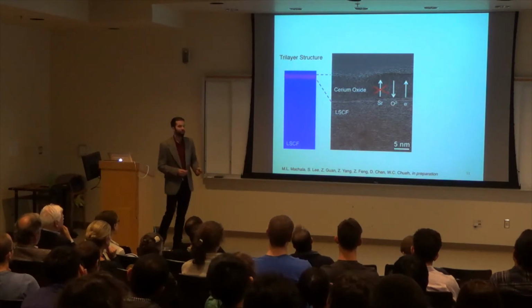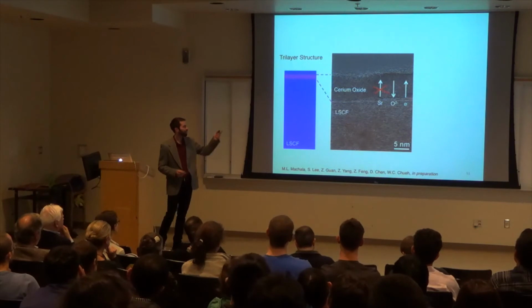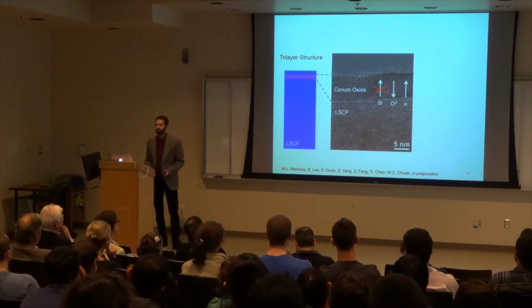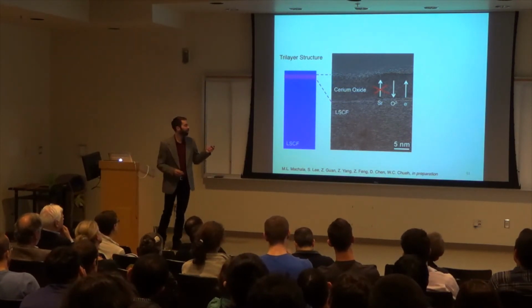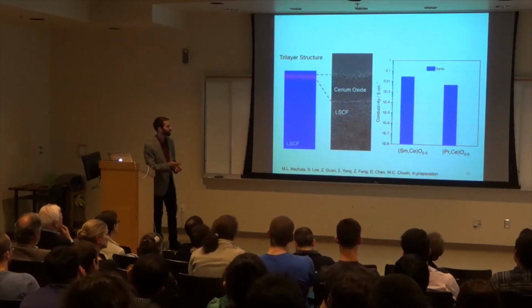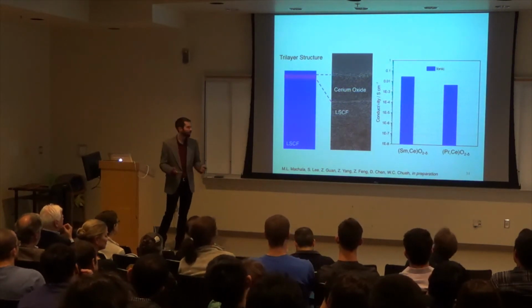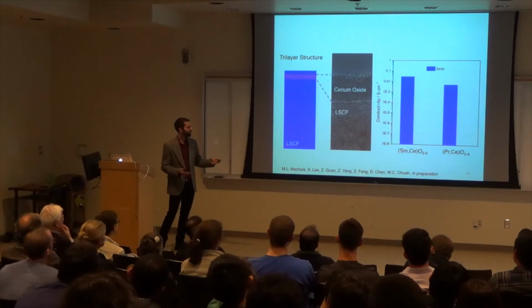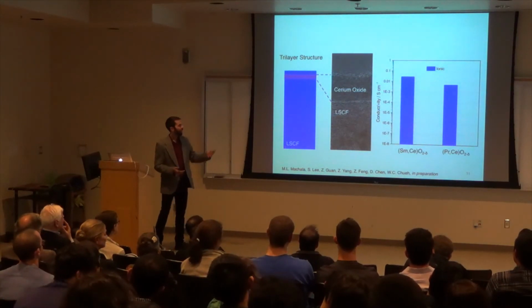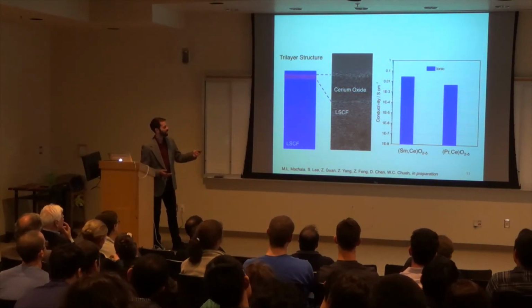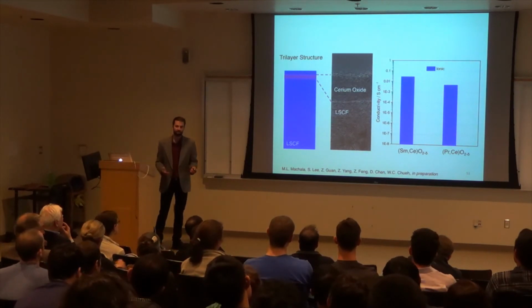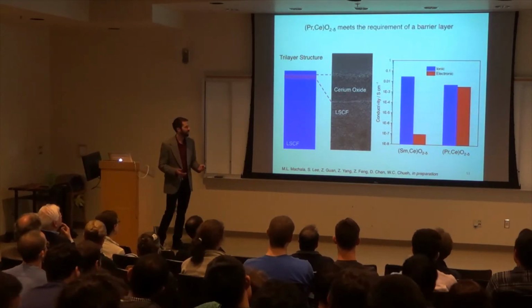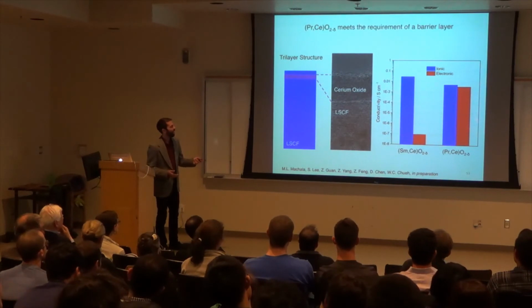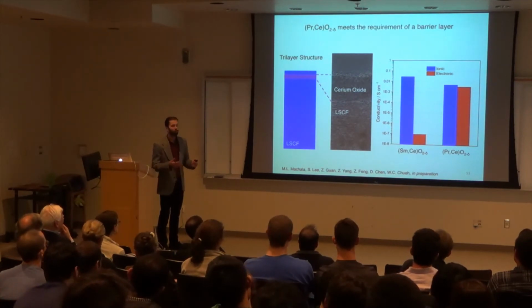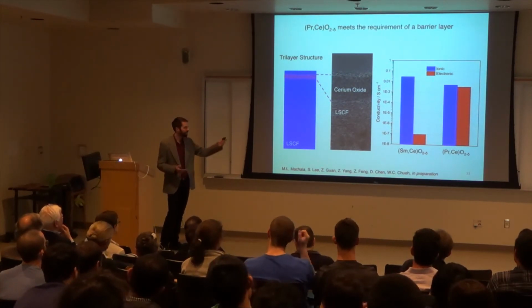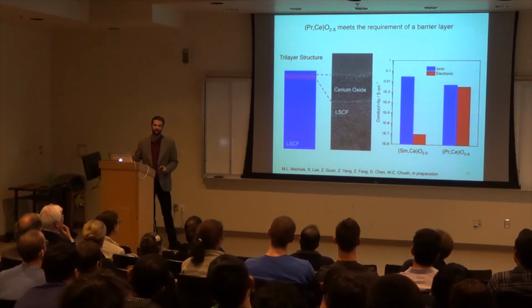Now, we also have to have 2 other requirements for the system. We have to conduct oxygen and electrons. And so what we do to accomplish this is we must substitute the cerium oxide, just like we did in the perovskite, with different elements. Here, samarium and praseodymium. And what we see here, this is the ionic conductivity in blue, and they're fairly comparable. But when we turn to the electronic conductivity, the praseodymium outperforms the samarium by 4+ orders of magnitude. This is because the praseodymium can change oxidation state, and this aids the electronic conductivity.